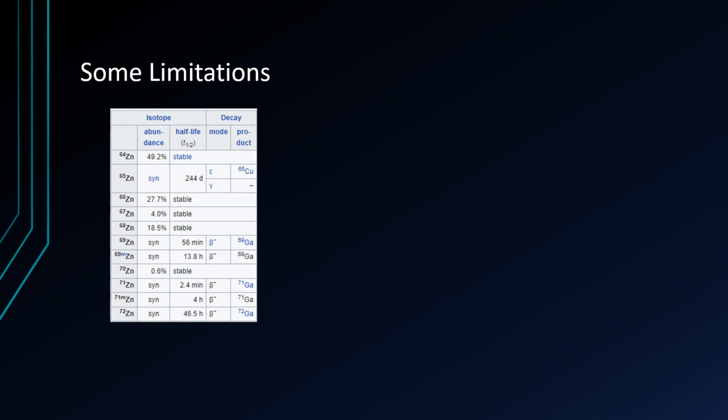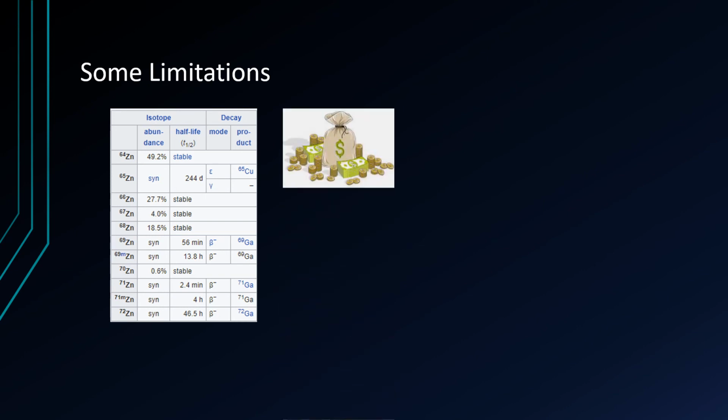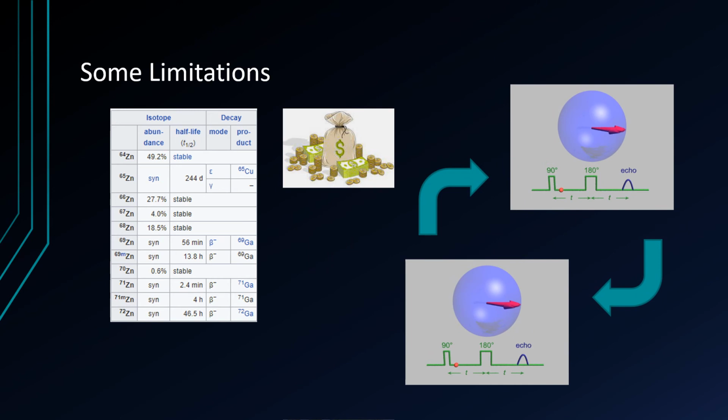The T1 spin relaxation time is limited by isotopic impurity and instantaneous diffusion. Isotopic impurity can be addressed with enrichment of material used to fabricate zinc oxide. Instantaneous diffusion, which also affects T2, refers to the coupling of donor spins to each other during the Hahn-echo process. Echo cannot cancel out this coupling because the donor spins are rotating together, but this effect can be minimized using smaller pulses. Another challenge is engineering with zinc oxide donor spins. Donors in bulk zinc oxide have the best coherence, but they aren't necessarily the best for device integration.